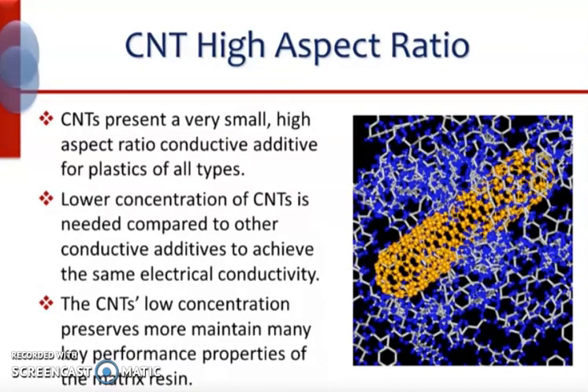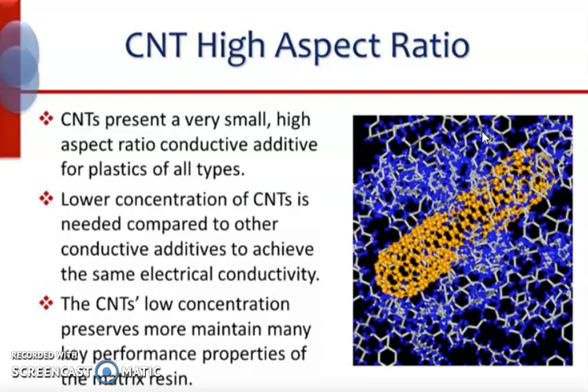Carbon nanotubes can also be used as an additive for polymers. In the image shown, carbon nanotubes are dispersed in an epoxy resin that can be molded into different structures. By infusing the polymer with electrically conductive carbon nanotubes and monitoring the electrical resistance at different points, it is possible to pinpoint the location and length of even the tiniest stress-induced crack. Once a crack is located, a short electrical charge can be sent to the area to heat up the carbon nanotubes, which transfers a signal warning of the presence of a crack on the surface.